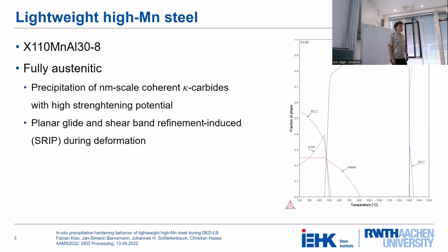So what are lightweight high manganese steels? We are looking at this kind of alloy. So it has 1.1% carbon, 30 weight% manganese, and 8 weight% aluminium. It's a fully austenitic alloy with the possibility to precipitate nanoscale coherent kappa-carbides in the matrix.